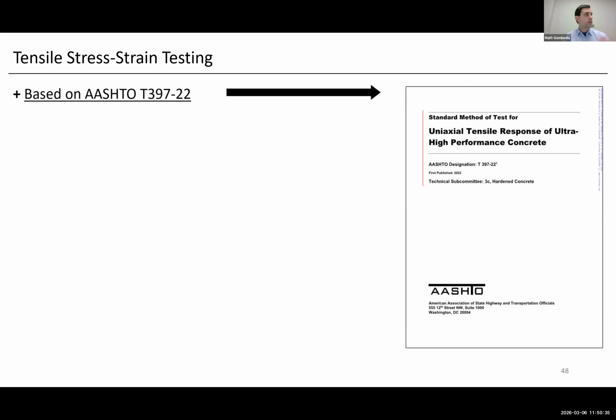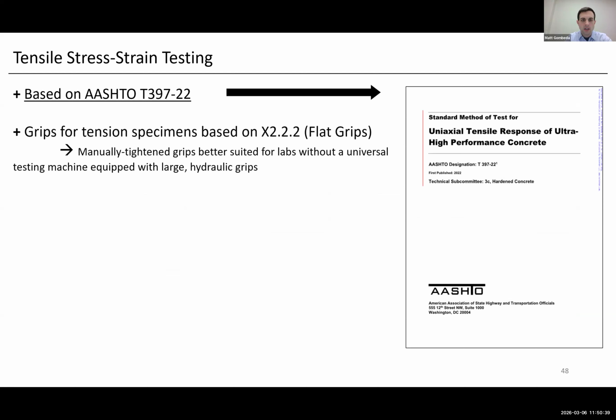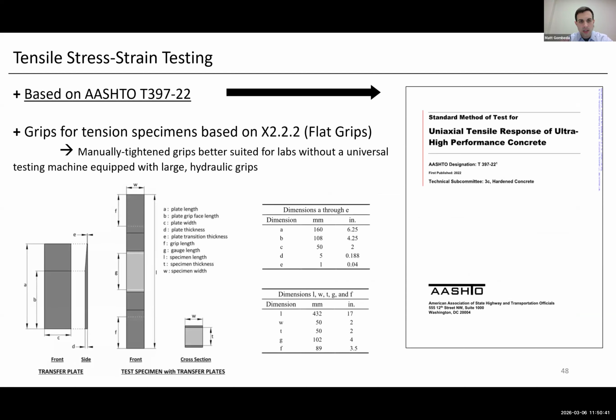And then we did the tensile stress strain testing with AASHTO T397. We used a manual grip setup because we didn't have a machine that had hydraulic grips large enough to accommodate the 2x2 specimens. And we wanted to also adapt this method to labs that maybe had similar issues, where they didn't have a ton of extra equipment to do these tests.